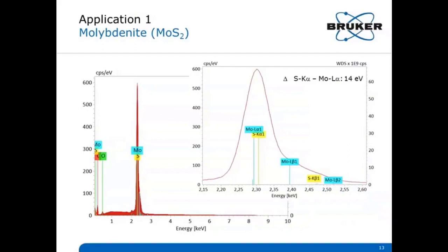Molybdenum disulfide shows a really strong pathological EDS peak overlap between molybdenum L and sulfur K lines. The energy difference between sulfur K alpha and molybdenum L alpha is only 14 electron volts. This clearly cannot be resolved by EDS. The peaks are too close together.